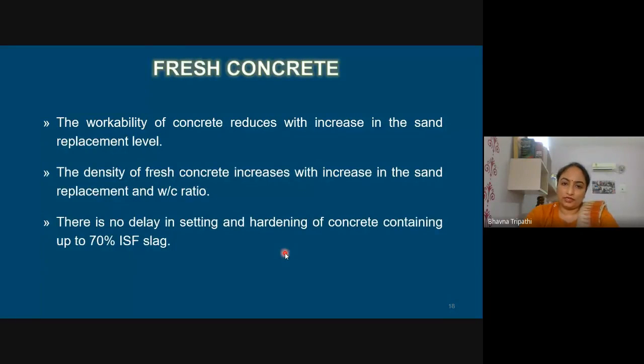The density of the mix slightly increased because the specific gravity of ISF slag was high. And one more very interesting observation of fresh concrete that I would like to share is there was no kind of delay in setting and hardening of concrete when we had added 70% of ISF slag also.